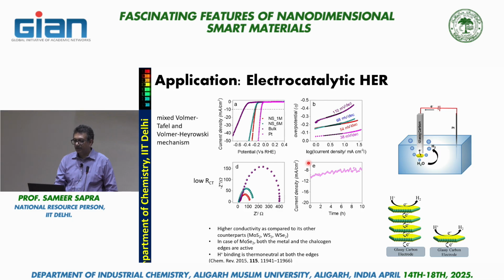All right, these devices are pretty stable, and I think all the EIS measurements is something that Professor Zain has already taught you. It so turns out that you see the red curve is for the one monolayer, and because it doesn't have to tunnel through, I've shown a schematic. The electrons don't have to tunnel through. It's a much faster process. It happens with much ease, and therefore it offers least resistance, least impedance to be correct.